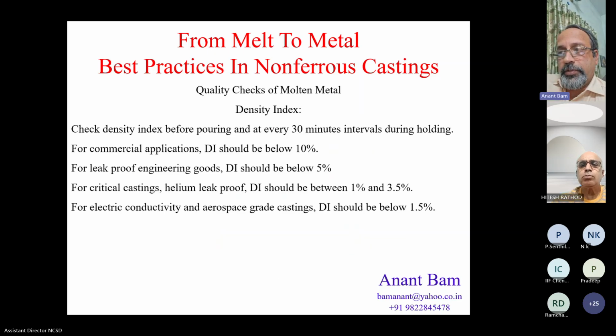Check density index before pouring and at every 30 minute interval during holding. For commercial applications, density index should be below 10%. For leak-proof engineering castings or structural castings, density index should be below 5%. For critical castings or helium leak-proof castings, density index should be between 1% and 3.5%. For electric conductivity and aerospace grade castings, density index should be below 1.5%.